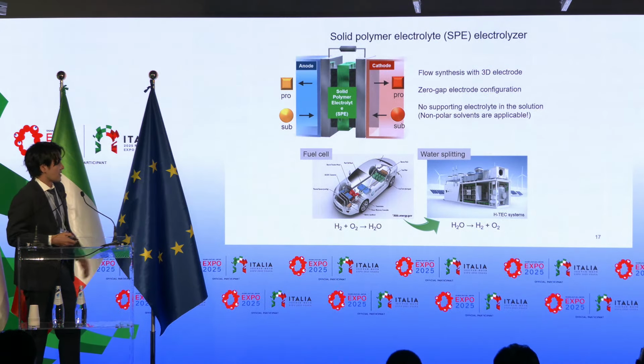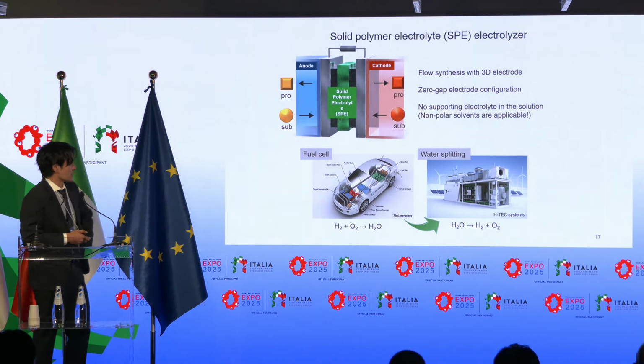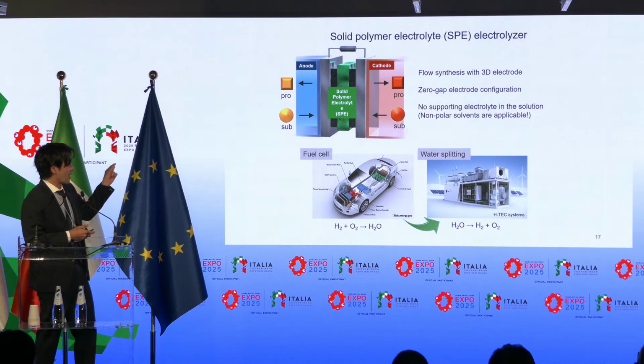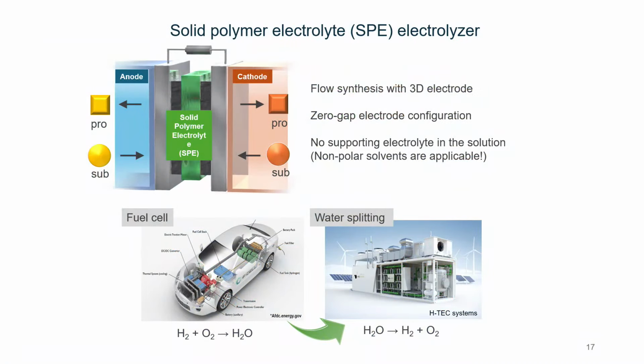Hayashida-san's presentation. And in this SPE electrolyzer, we are using a thin membrane, SPE membrane, and sandwich the membrane with the electrode. And the electrode is three-dimensional, so it has a really large surface area, ensuring fast reaction kinetics. And also, thanks to the zero-gap electrode configuration, we don't really need to add any supporting electrolyte. And the energy efficiency could be very high. And because we don't need to add any supporting electrolyte in solution, non-polar solvents like benzene, hexane, or toluene could be used for the electrolysis, which is not possible for the conventional electrolysis process.